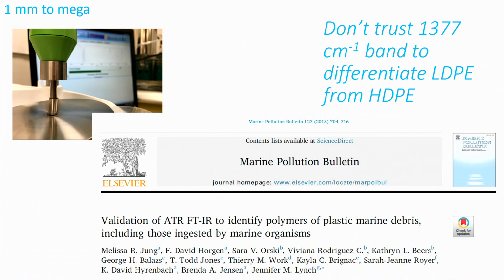Two years ago, we published this study with our colleagues at NIST in Gaithersburg, Maryland, validating the very cheap, easy, fast method of ATR FTIR to identify polymers of marine debris plastics. And we found that it works very, very well. We actually talked about how well it can do at differentiating the different densities of polyethylene, high density versus low density polyethylene. Since then, we've decided, don't trust us on that one. So we want to get that message out there.